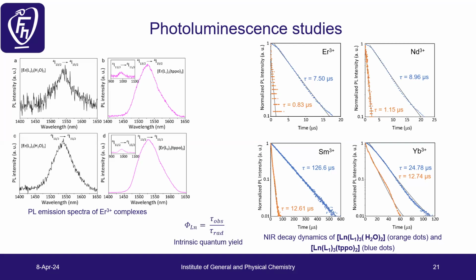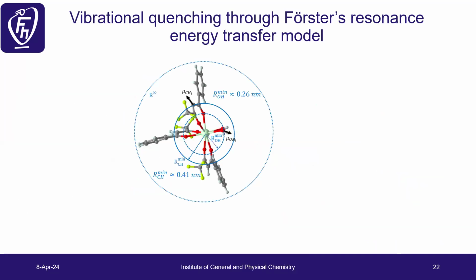Why? We also calculated the intrinsic lifetime quantum yields, so lifetime and radiative lifetime. You can see also a significant increase. Why is this happening? Because we can see here on the crystal structure that we have the radius of CH and OH. What we found is that the closest CH and the closest OH group contribute the most. Even when we introduce the triphenylphosphine oxide, which is quite bulky, and we introduce more CH groups, we reduce the OH group, but the concentration of CH groups doesn't influence the radiative lifetimes.